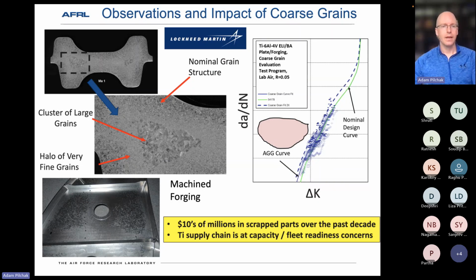that's expected. One of the problems is you can't detect these until you go through the whole process of producing the billet, forging it into a part, heat treating, and then you spend all the money to get down to this final machine state, and then that's when the grains are uncovered. There's auxiliary efforts looking at how can you do this non-destructively, and so I think there is some actual ultrasonic response that differentiates the fine grained regions from the coarse ones. So there may be a path there, but nothing that's kind of production ready at this time.